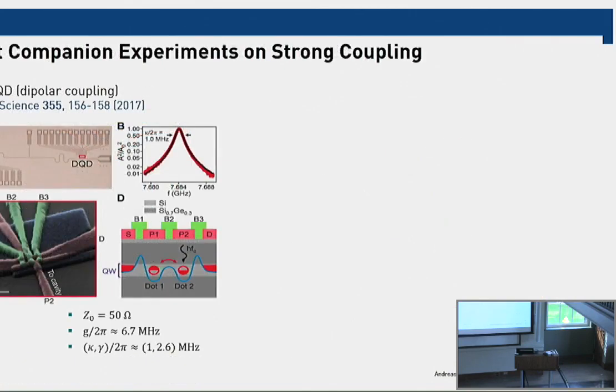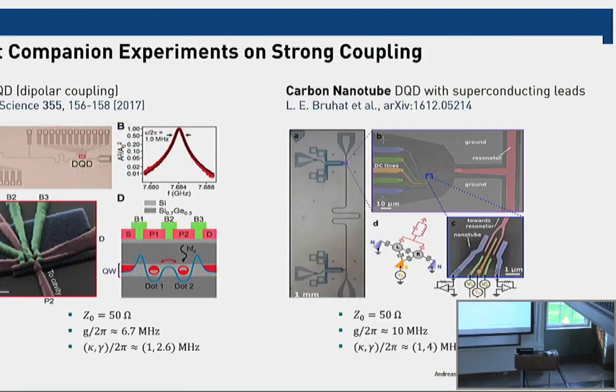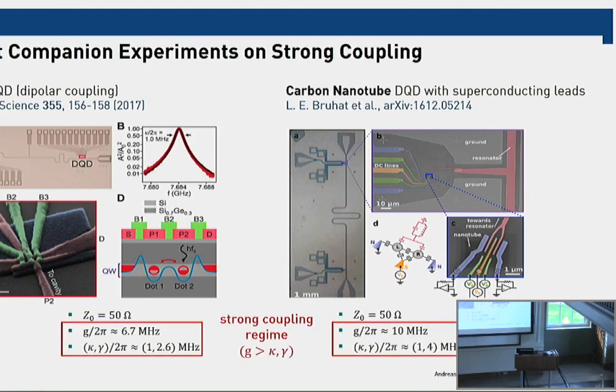And so that motivated us to also look at second generation devices. And here I should mention that there's this nice paper from Jason Petta's group that does that on silicon germanium quantum dots, and that was published in Science in the beginning of the year. And there's also a paper by the ENS group of Takis Kontos from Paris using a slightly different approach. And both of them just made the strong coupling limit, both with 50 ohm resonators, but slightly smaller, slightly better coherence properties, so better line widths.